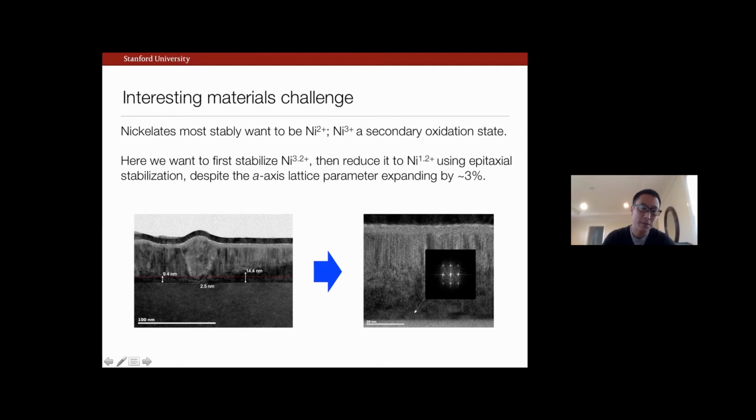95% of the volume of the film was decomposition products, secondary phases, or a mess. And we believe that the partial superconducting transition was this first few nanometers at the interface. So by some work, we were able to expand the stability region of this infinite layer structure. And here we could achieve complete zero transitions in transport.